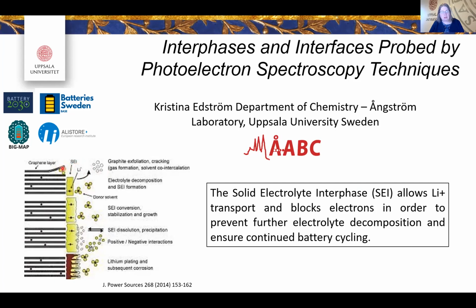At the start, when people started to try to use graphite at the beginning of the 1990s, the organic solvent molecules and the salt co-intercalated and started gassing the batteries and exfoliating the graphite. And then the right kind of electrolyte solvent components were found, and this could form this solid electrolyte interface, which grows to a thickness where the electron cannot tunnel through it. And by not being able to tunnel through, it's not continuing to degrade the electrolyte, so this reaction stops that degradation.